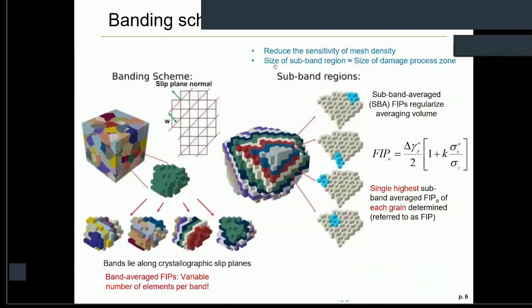So let's see also some models. You know that FIPs should not only be the local FIP value. We should also consider the non-local FIPs like this. From one single grain, we build up the slip band based on the grain orientation. So depending on the slip systems, we can build up the slip band. And also we calculate the slip band average FIP in order to predict the slip band fatigue crack initiation.